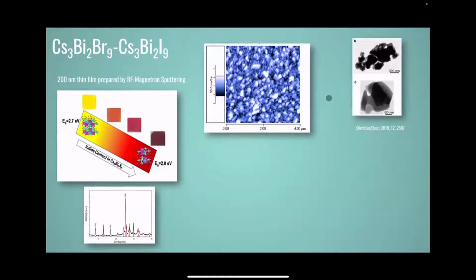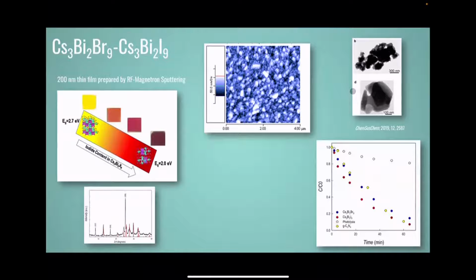We also prepare some nanocrystals, and we already tested them for organic dye degradation with methyl blue. And you see the pure perovskites in the photodegradation are quite effective. They are as effective as pure graphitic carbon nitride. So now we are moving to photocathode fabrication with pure materials, but more interestingly with the heterostructures.